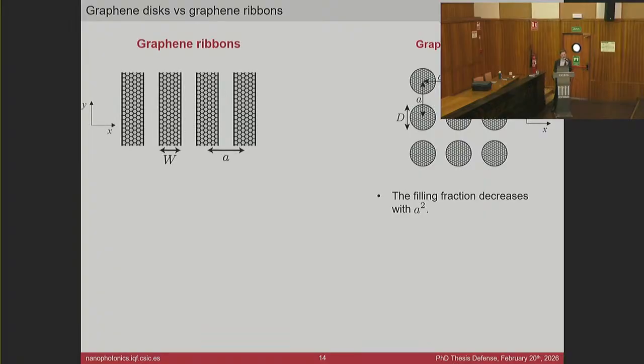Now, I have shown you the possibility of exciting lattice resonances in periodic arrays of graphene disks, but we've seen that it has some steep dependence on the period. The filling fraction decreases with the period squared, and for this reason, maybe it will be interesting to explore an alternative configuration, like this array of graphene ribbons, in which the filling fraction decreases with the period. However, there are more differences.